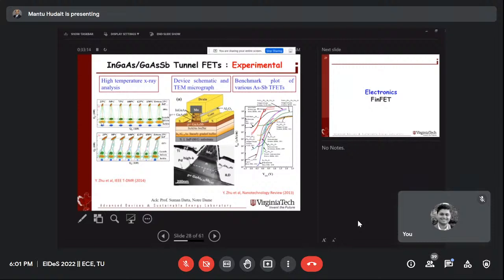So my students and I sat down and asked, can we do an in situ X-ray measurement? Please remember, you put the device stack on the X-ray machine, you collect the data at room temperature, and you keep hitting it, collecting, keep hitting it, collecting. This kid was present, I believe, 36 hours to collect this data. Please watch here. He increases the temperature, stabilizes, measures X-ray. There are no material issues.